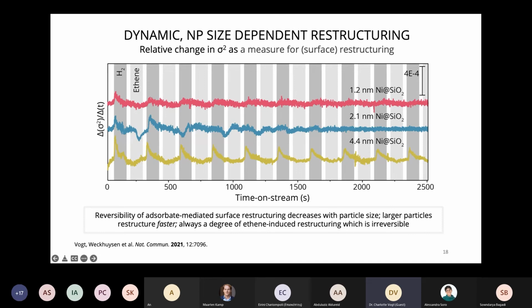So the 4.4 nanometer particle that we measured restructures much faster than the smaller ones. The reversibility of the restructuring actually decreases with particle size. You see the first peak is always the highest, but for the smallest nanoparticle size, after that first peak, it's quite difficult to distinguish others afterwards. So there's always a degree of restructuring that's irreversible because this first peak is most intense. So these are quite interesting observations, and especially the fact that larger nanoparticles restructure faster, we were able to